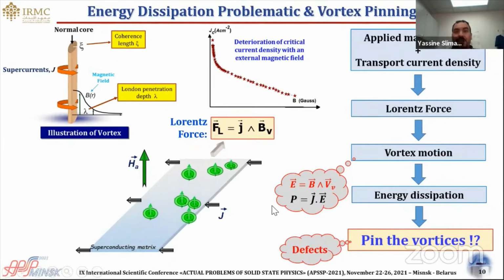To minimize this detrimental effect and improve the electrical properties of superconducting materials, the vortices must be pinned. To achieve this objective, the generation of efficient structural defects inside the superconducting matrix could be a possible way. These generated defects, if well distributed, can allow pinning the vortices in their places and thus prevent energy dissipation.